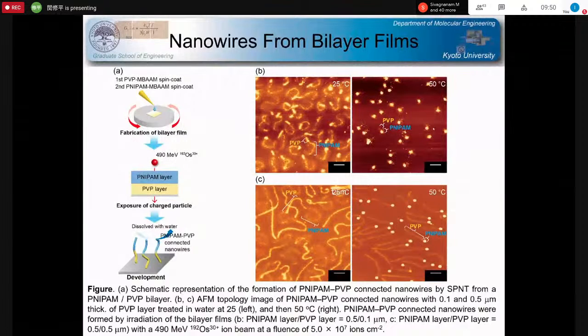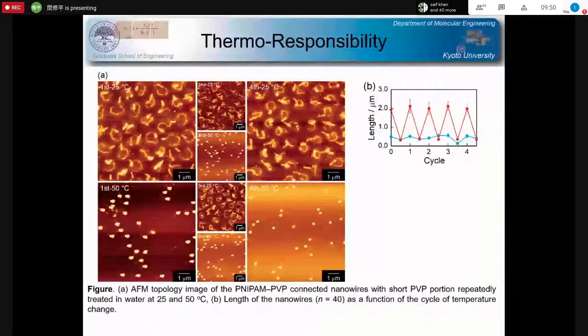And very interestingly, one part of the nanowire was thermal responsive. So against the temperature control, only one segment of the nanowire shrank, and then it stretched again. So this microscopic observation clearly suggests that the nanowire was composed of two completely distinct polymer substances.